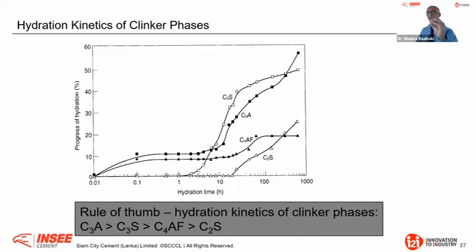And you will come, for example, I will show you how the ASTM has a type of cement that is for low heat cement. And you will see where the specifications are when it comes to C3S and C3A. Okay, and for long-term strengths, we know that the C2S, that produces the same hydrated product as C3S, will not contribute at early age strengths or maturity. It's mainly coming from the C3S. This is why we need to have the right optimum mix in order to fulfill some application requirements.